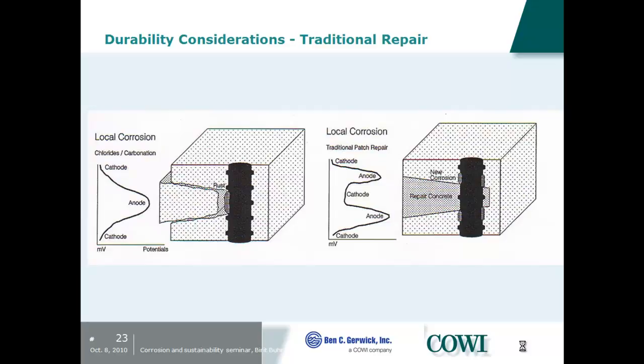So I think they also have it now that the amount of chlorides you have left in your parent concrete should not exceed 0.1% by weight of concrete, something like this. And if it does that, it's an okay system, it works. And then you ask, what about the zinc in there? They did tests themselves in England, where they found that it did not expand significantly, so it did not spall, because that would be a concern to raise. So they work, but you have to know where to use them and to which extent.